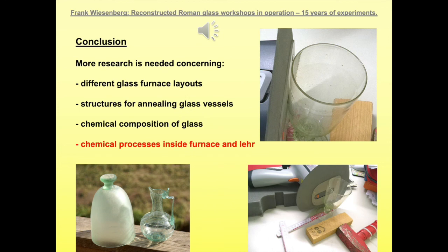Another detail we have noticed before, which I've mentioned already, is the dulling of the surface of some glass vessels, especially in England at Borley and also at the small annealing oven at Welsica. This is an effect which seems to build up inside the annealing oven due to some conditions which we haven't fully understood yet. So more research has to be done on this effect.